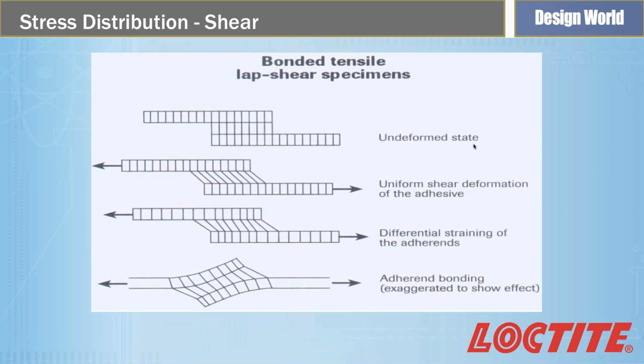And here's a little bit of why that happens. This is kind of an old graphic, not as nice as the other ones, but I think it really speaks to the point. In this case, this top set of rectangles here is the substrate. This one in the middle is the adhesive, and this one on the bottom is the substrate again. So as you apply that shear force, you can see the adhesive starts to move. And if you look at this under very high-powered, close filming under an actual Instron, or when you're mechanically testing it, you'll see a little bit of substrate distortion happen, and that creates not a true distribution of stress. So, in a perfect world, if that little distortion didn't happen, you probably would have perfect distribution of stress. Because it does, you get that concentrating at the leading edges, and this is why.